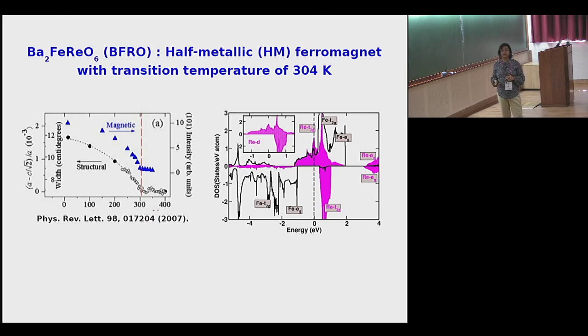If you calculate the DFT electronic structure of this bulk material, which is shown here, the plus and minus being the up and down spin channels, and the zero of energy set at the Fermi level, you see that the iron d states, shown in black, are completely filled, while in the up-spin channel the rhenium t2g states, strongly hybridized with the iron t2g states, cross the Fermi level, therefore making it a half metal because it's conducting in one spin channel and insulating in the other. So that's the bulk electronic structure.